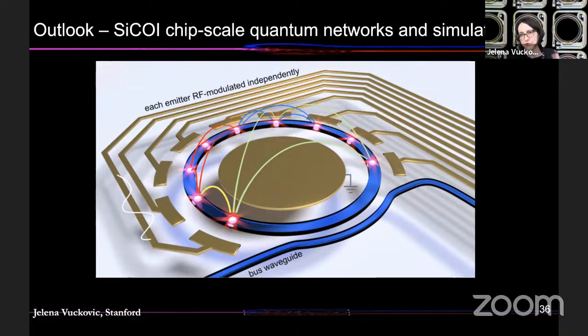And also we run constraint optimization, which means there are minimum feature sizes and a lot of other things that we incorporate. Having said that, we probed this problem for a variety of different initial conditions, and even for these wavelength splitters that are much more compact than traditional solutions, we found, for example, 6 solutions with the same efficiencies in the same footprint, which means that everything that we work with in photonics is highly suboptimal. There are a lot of better solutions that are more robust to errors and have smaller footprint. Landscape depends on the function. So when you change the function, go to a different device, the landscape can be completely different.